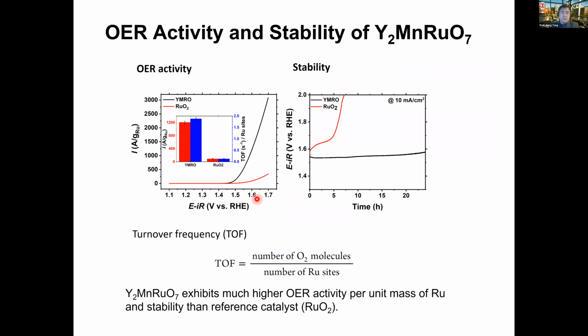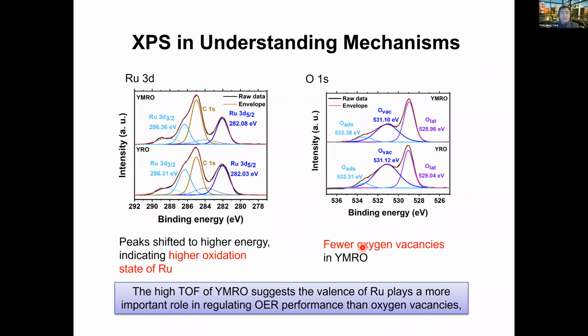This is again the comparison, but using a different technique as well. Besides the comparison of activities with reference to ruthenium oxide, we also did a comparison of stability studies, and at a typical 10 milliamps per square centimeter, it maintained good stability as well. This work I think we just got published, so if you're interested, I can probably send you the ePrint at some point.